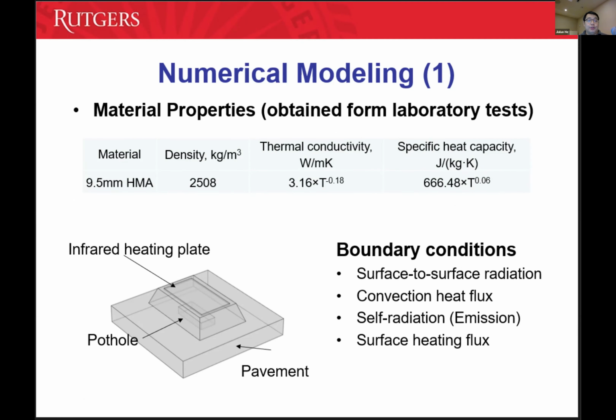So first we conduct laboratory testing to get the thermal conductivity. Although we do have some data available, in this case we want to emphasize that the thermal conductivity does change with temperature. So we measured the thermal conductivity at different temperatures, and we found there's a nonlinear relationship. So you are expecting the thermal conductivity and also the specific heat both to change with temperature. These are quite important in order to get accurate temperature prediction. And then you can build a model with boundary conditions. Basically, we consider normal solar radiation if we have temperature data or weather station data, and then you have convection with the wind, with the wind velocity effects. Then you have the self-radiation, and then you have the heat flux coming from the infrared heater.